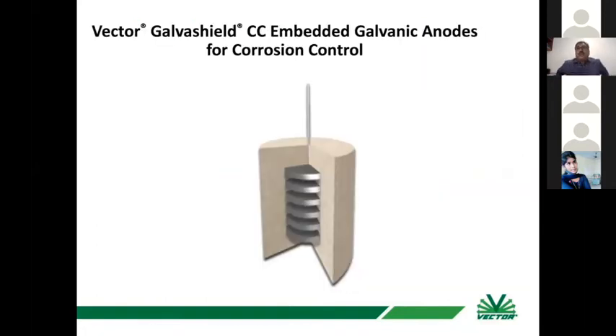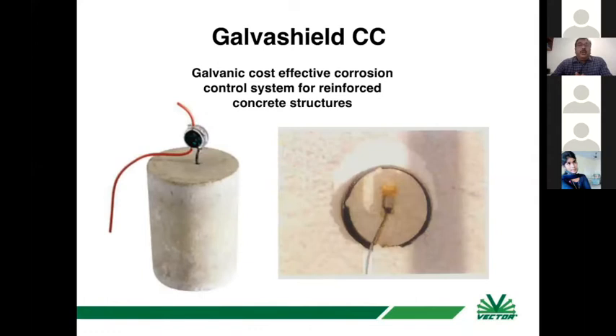So this I had shown you where there is a patch already spoiled and there are cracks. But while doing your NDT, you come across that the structure is good, cracks are not there, but there is contamination ingress. In that case, you need a high initial current and you want to control the corrosion. So you need a different type of anode which can be drilled and inserted inside with special connectors.